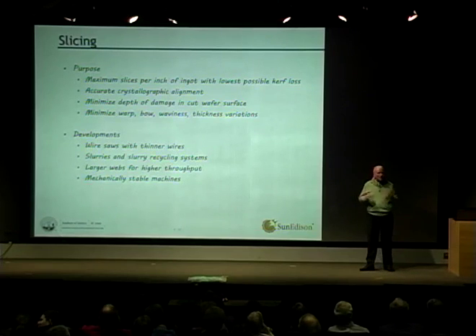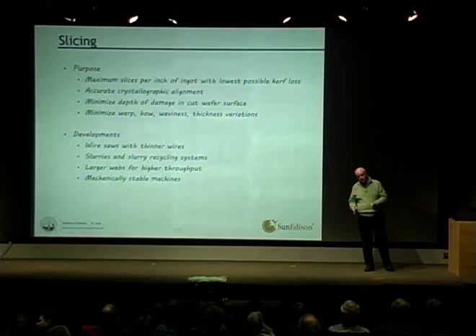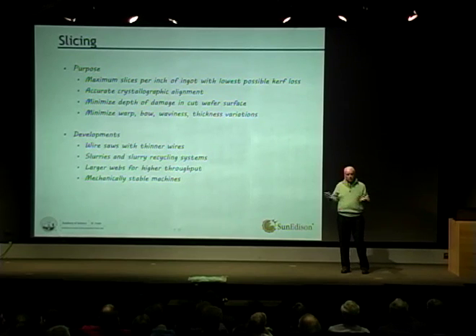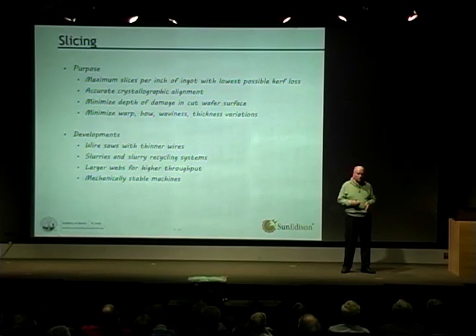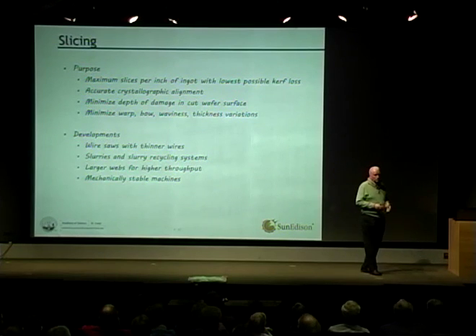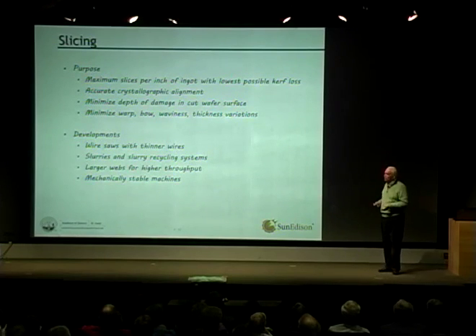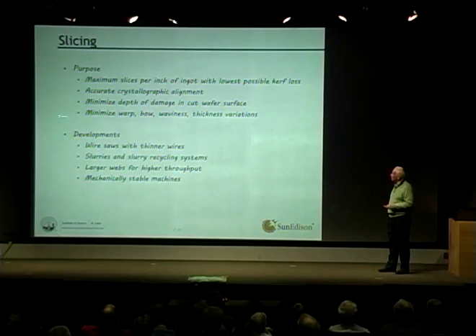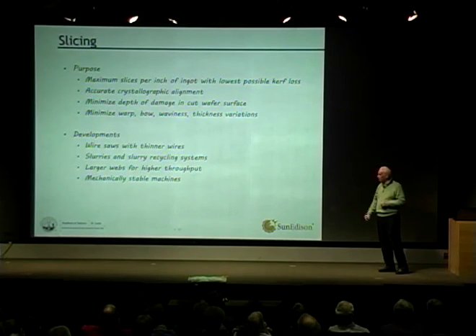But the problem is, ideally, what we would do is cut the crystal into wafers and ship it. But as you'll see, when we cut it, the surface isn't perfect. It's rough, it's got damage on it. It's a little bit flat, but not perfectly flat. You try to make it as flat as possible here. This is what this one means: minimize warp, bow, waviness, thickness variations, and so forth. You're trying to make it a very flat wafer. It's hard to do when you've got wires like that that can vibrate.